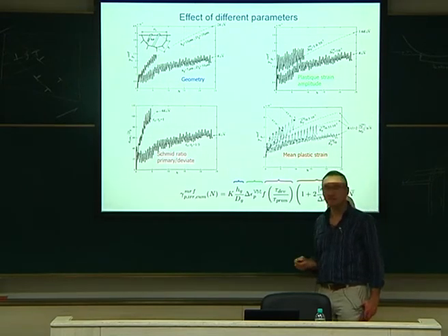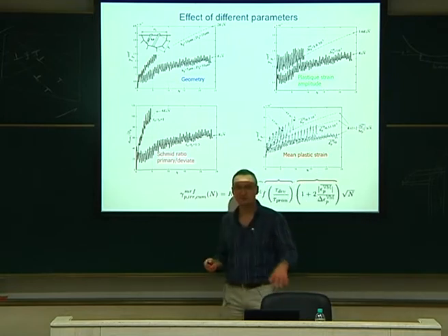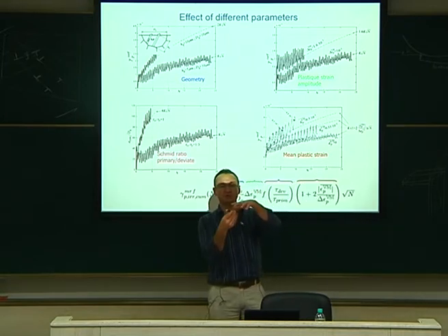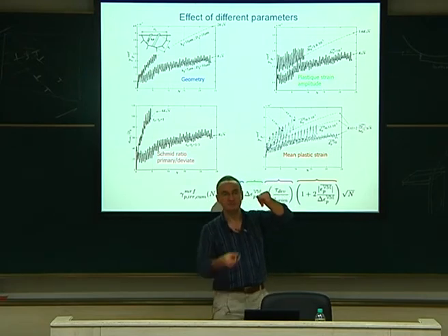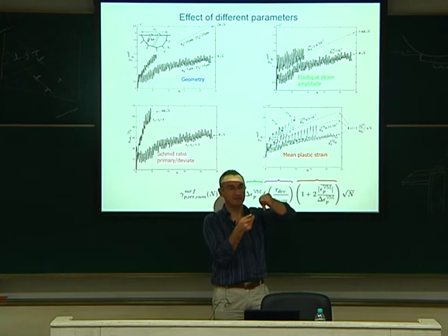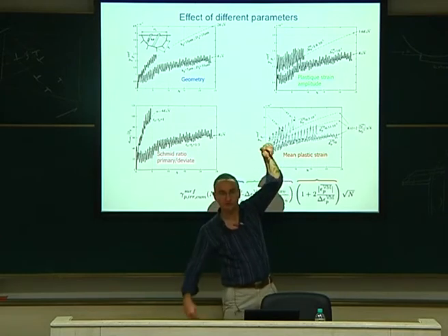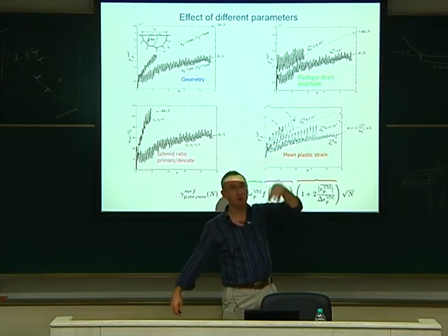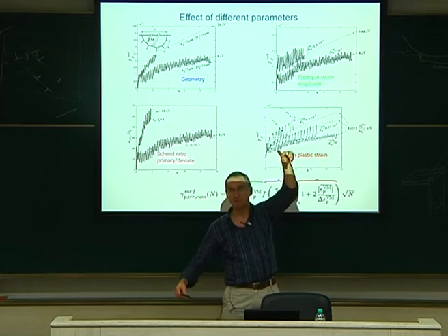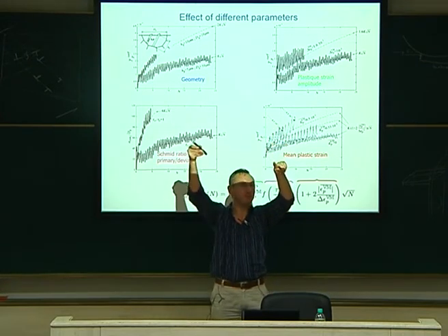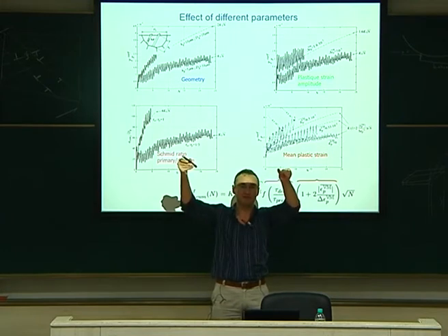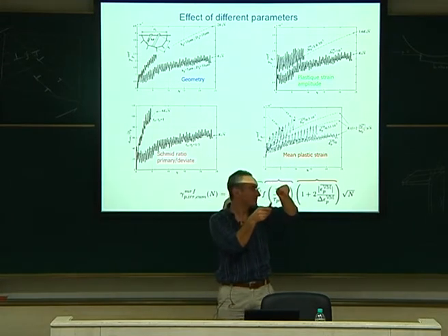Okay? This we can understand easily. It means that if a dislocation comes out and creates a step, this step will be removed only if you have the opposite dislocation coming in the exact same plane, okay? Now if the grain is very big, your dislocation is coming out, so you have the front loop in the grain boundary on the bottom. When you unload, these guys will come back, but since the path is huge, it may have some cross-slip and reach another place at the surface. Not the same place. So it will not remove the step.